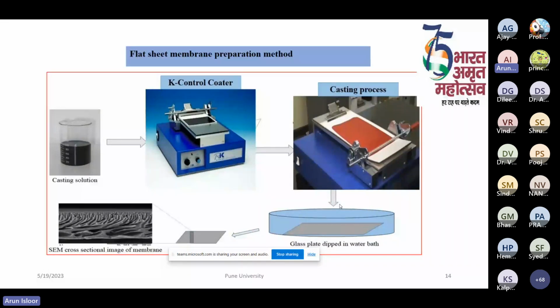However, with the automated instrument, we can fabricate the membranes very precisely, at about 25 micron, 50 micron or 100 micron thickness. But for beginners, if you don't have sufficient funding, then as I mentioned, you can start with a glass plate and a stainless steel or glass rod. With the help of that, one can begin.